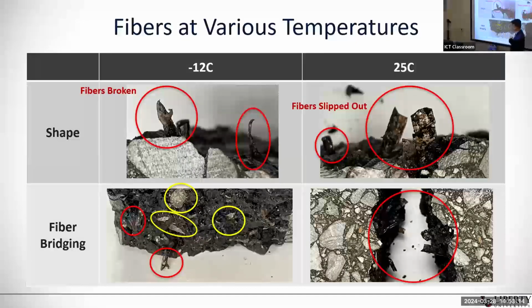Right up to the point that the cracks start and propagate suddenly, a higher load stress is applied near the crack tips, which acts like an impact and just breaks the fibers close to the crack tips. So it's probably not very obvious further away from the crack tips.